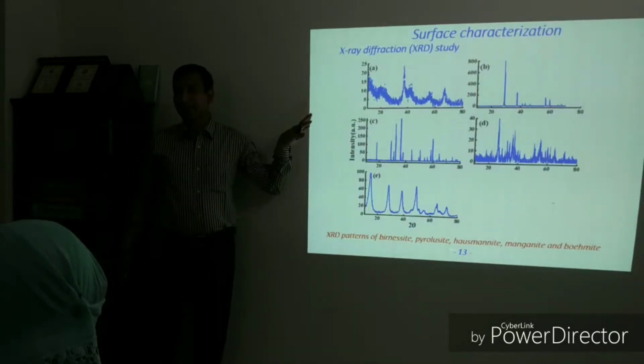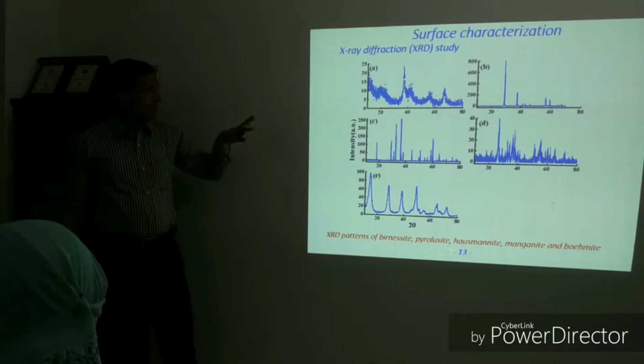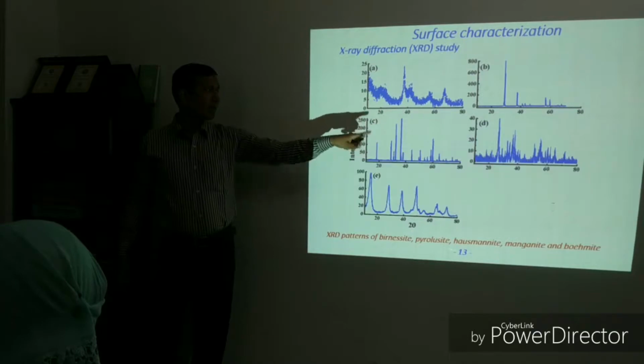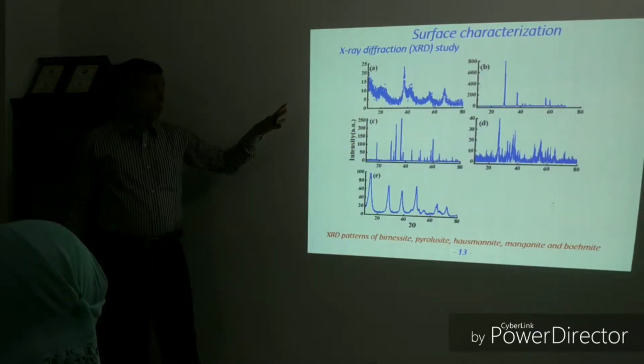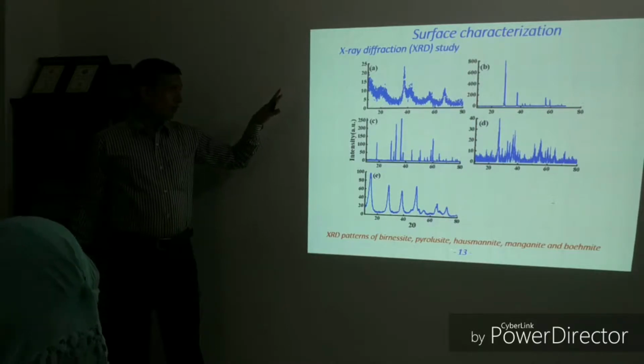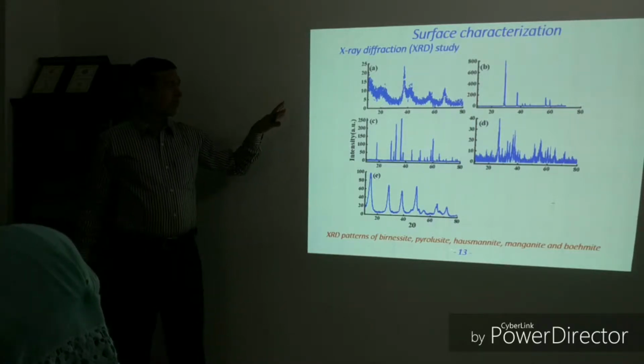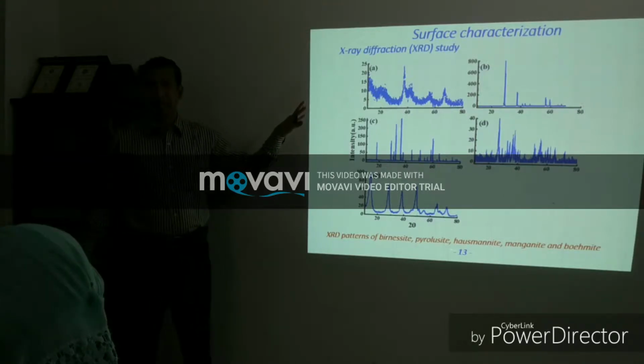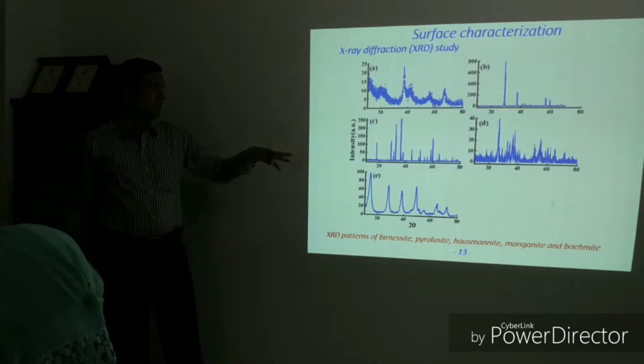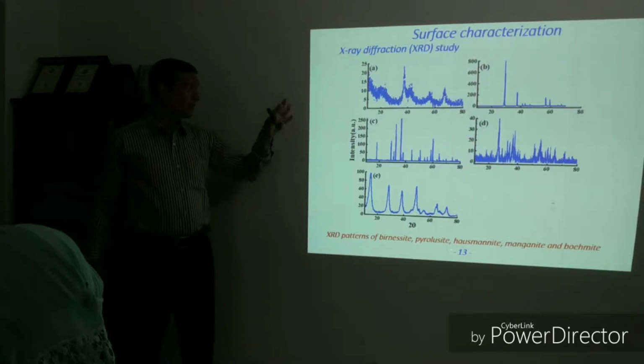Then surface characterization, XRD. So these are the typical XRD patterns for birnessite, pyrolusite, manganite, and boehmite. From this figure, it is clearly seen that for birnessite and manganite, the peaks are relatively broad and not too intense. This indicates that these two substrates are amorphous in nature. On the other hand, in case of pyrolusite and boehmite, peaks are relatively intense and sharp, indicating crystalline nature.